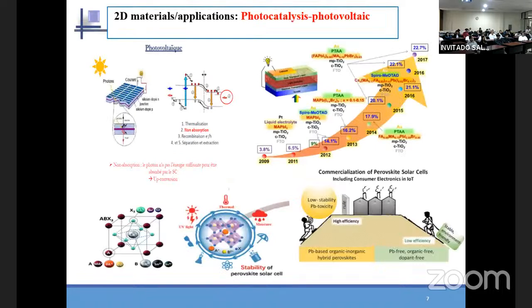The first example is photovoltaic application, where we need a semiconductor material having a band gap whose value must be close to 1.5 to 2.5 or 3 electron volts for the visible range. In this semiconductor, an electron in the valence band can absorb visible light to be excited to the conduction band, and so photocurrents are created. The first example for solar energy, as you know, is silicium, and then we have different compounds like perovskites, known for interesting stability, good absorption, and good efficiency. But the problem with these materials is that some perovskites are not stable, and they contain toxic atoms.